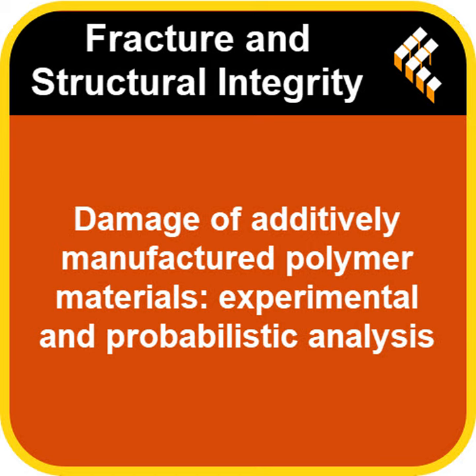Remember the white base coat and black spray pattern? Yeah, the speckle. They actually tested samples with and without that coloring across all the print orientations. And what did they discover? Did painting it make it weaker? Surprisingly, no. The stress strain curves, which show how the material behaves under load, were almost identical for the colored and non-colored samples. Really? Yeah.